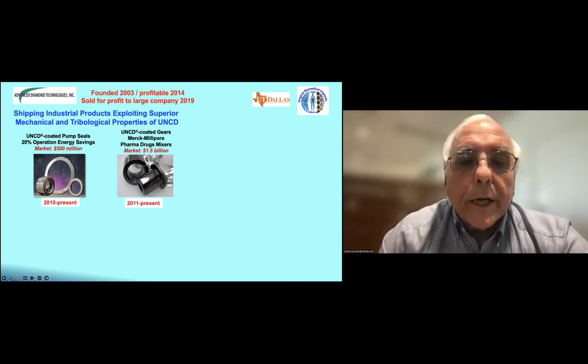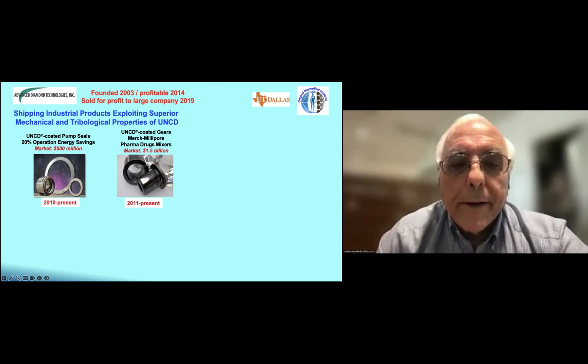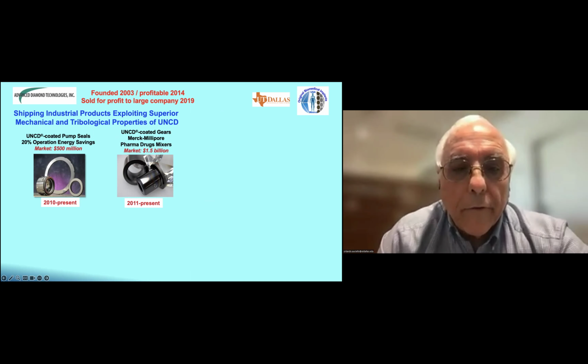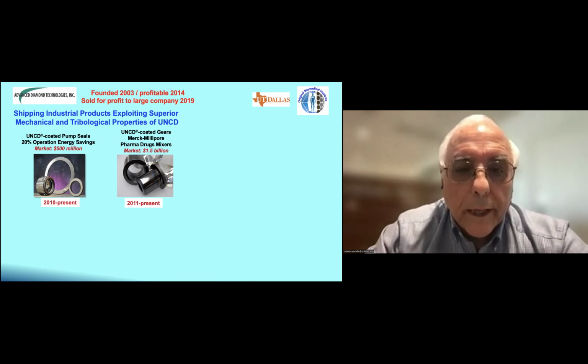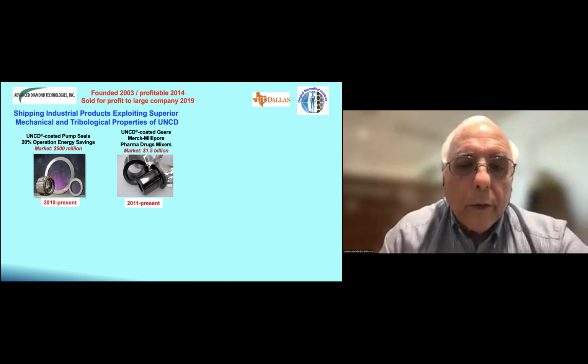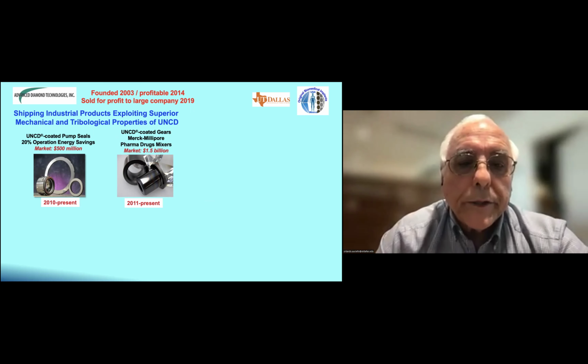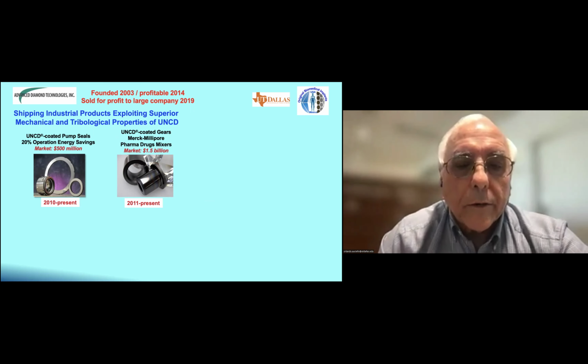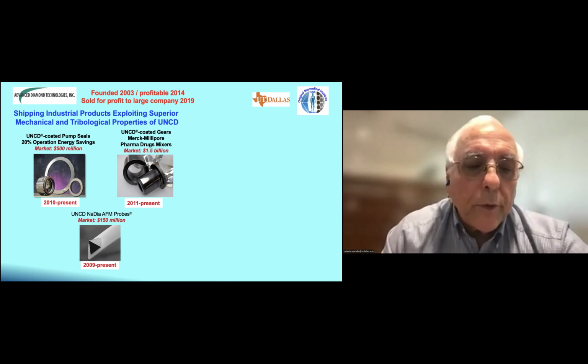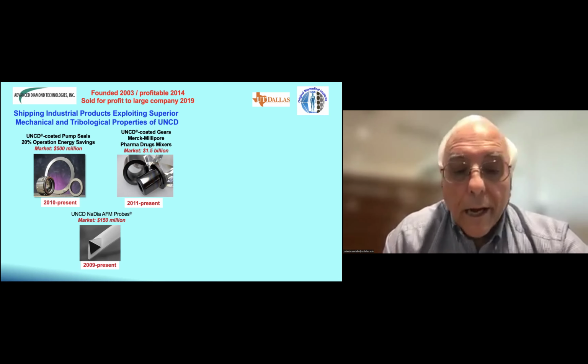Then Merck Millipore came to us because they were having problems with the bearings, both from biofouling, to produce pharmaceutical drugs. We coated with UNCD, and they have been buying our UNCD coating since 2011 because there is no biofouling and there is no degradation. The other thing we developed is a NaDia probe, which is an atomic force microscope probe with UNCD coated on the silicon tip. And this probe, you can have it for a long time because it doesn't degrade like the silicon tip when you do AFM.